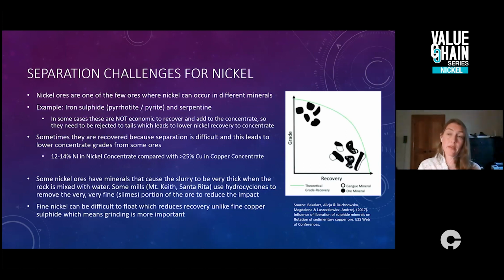So when we look at some of the historical and typical nickel concentrate grades, they tend to be a bit lower than, say, concentrate grades in the copper industry. A traditional nickel mill would deliver something in the 12 to say 14 or 16% nickel in concentrate, and that compares to over 25% copper in copper concentrate from a copper mill. And that is solely because we have nickel present in other minerals that adds to the overall nickel recovery, and it's economic to recover them to some point, but at some point we have to stop.